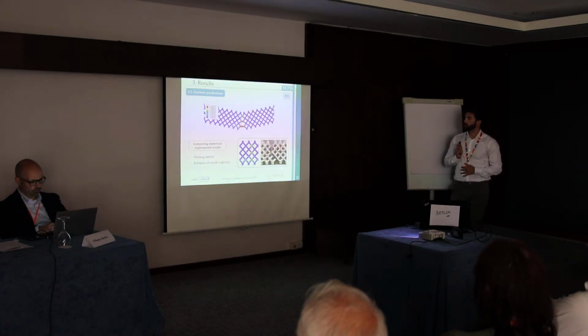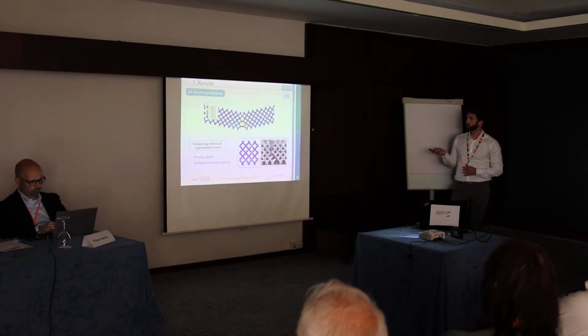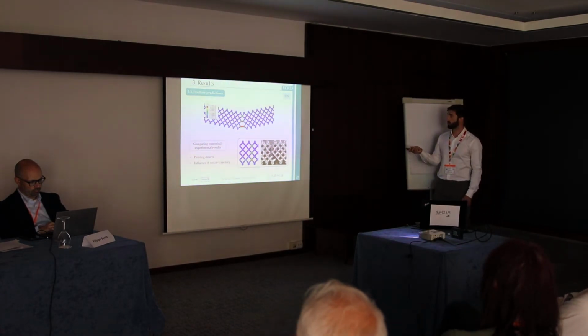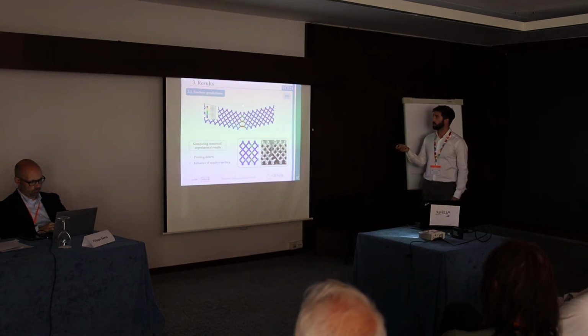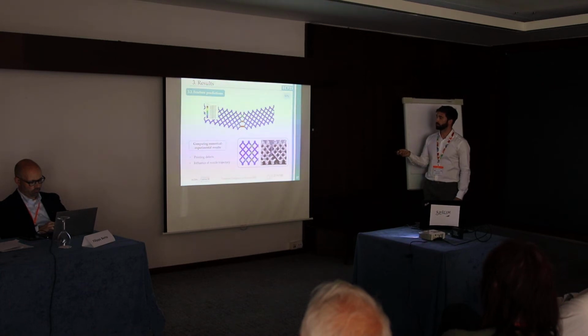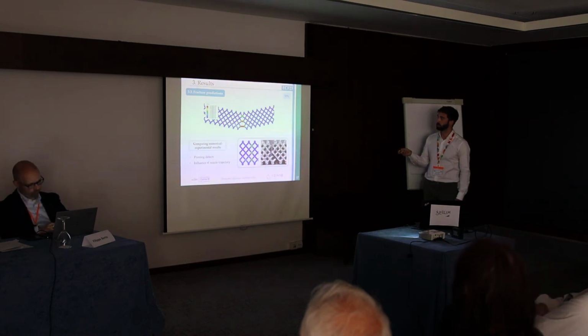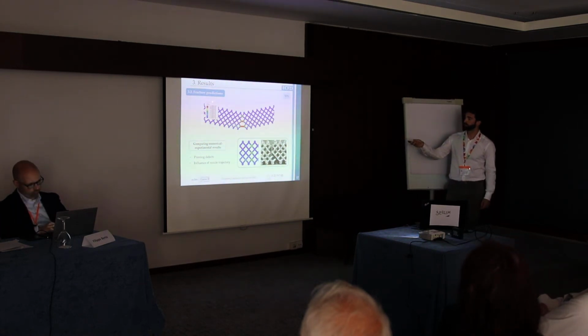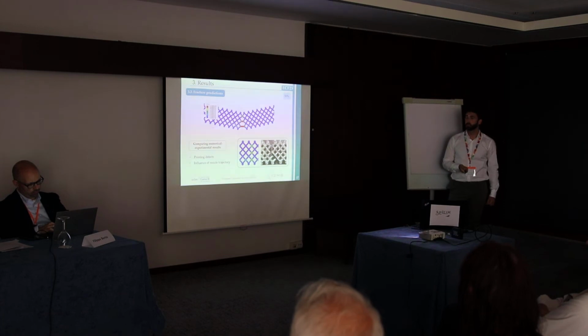So, talking about the fracture predictions, this is the result of the preliminary simulation. Okay, this is as we expected. The crack path simulated runs along the minimum cross section next to the middle of the specimen. And remember, this is the value of 1 for the phase field parameter. That means that the material has lost its strength.